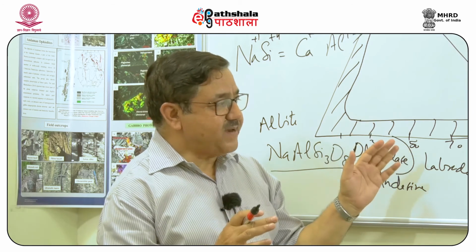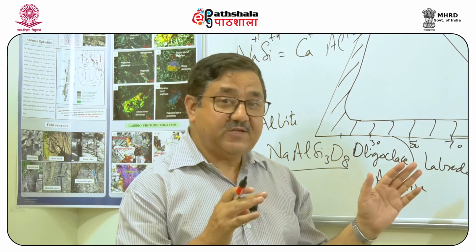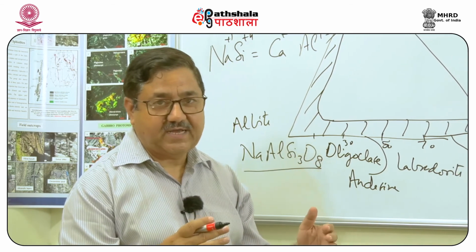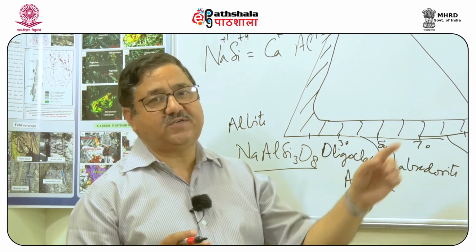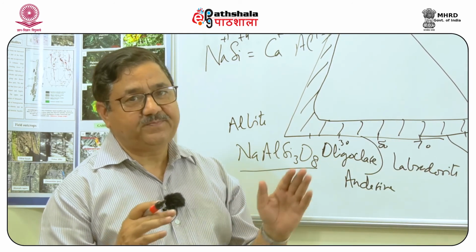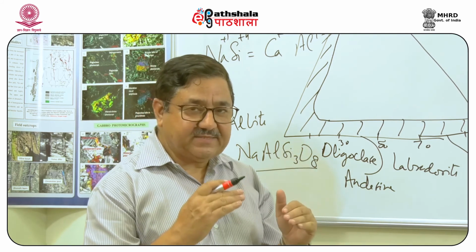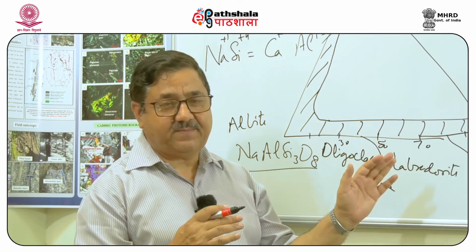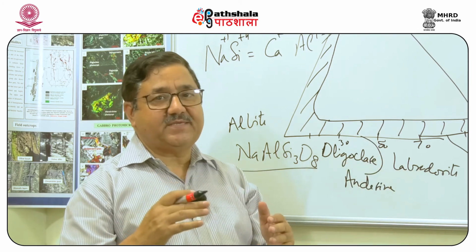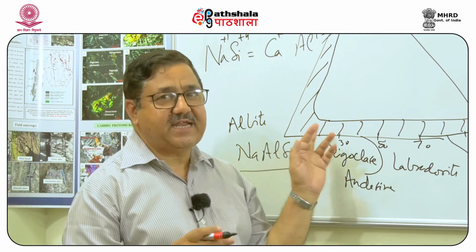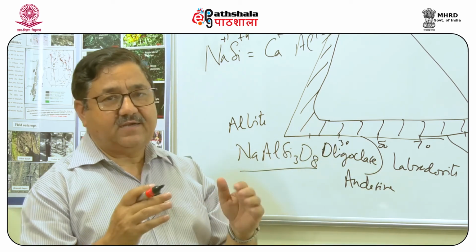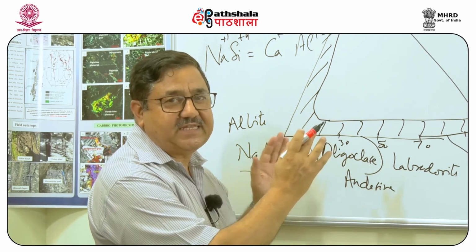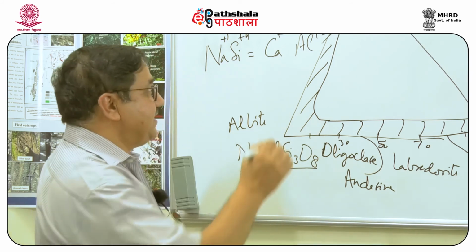Now, this behavior is not supported when the feldspars are forming in the solid state in metamorphic rock, that is, 100% solid solution is not observed in them. Because of that, when a sodium feldspar is becoming increasingly calcic feldspar with increasing temperature during metamorphism, there is normally a 10 mole% gap, from the oligoclase composition to the albite composition, where there is a jump, and that is known as the peristerite gap.